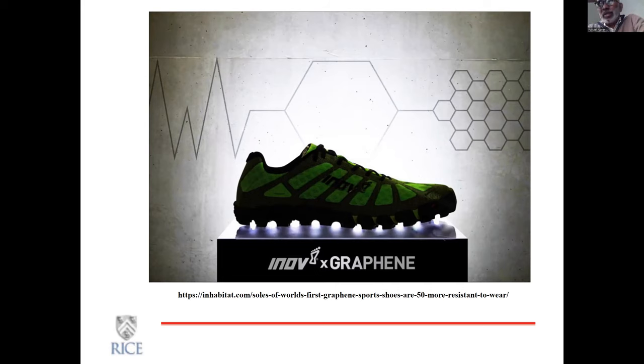And it's carbon, so density-wise, you have an advantage. In many of the composites, I feel the density is a big issue, and carbon being low density allows you to get that specific property advantage. We talked about electrical conductivity and strength, but if you look at specific properties, specific conductivity, specific strength, specific modulus, then these nanotube or graphene materials are hugely better, because most of the metals are heavy, and MXenes are essentially metal-based. And in terms of sustainability, carbon is considered to be a very good material. So we all accept carbon in many ways.